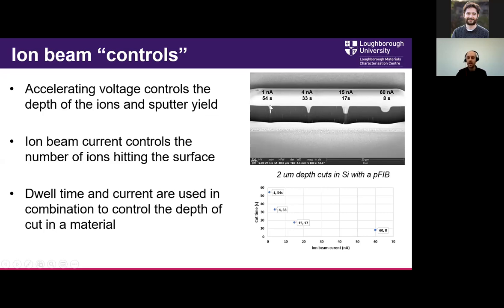So as we increase our current, here you can see a little example of a cross section of some lines that we've cut. At low current, we have quite a nice sharp probe shape. And as the current is increased up to, this is 60 nanoamps, so high current, the probe shape isn't as sharp anymore, but we can make a much larger cut in a much shorter period of time. So by controlling the current, we can control how quickly we cut an area. If we want to cut a very large area, we would use a very large current. And if we need a small, accurate cut, we'd use a very low current.